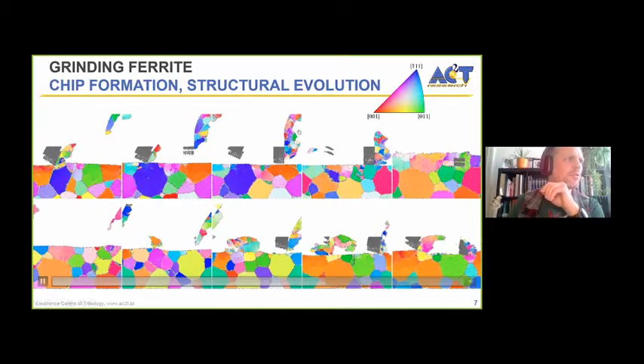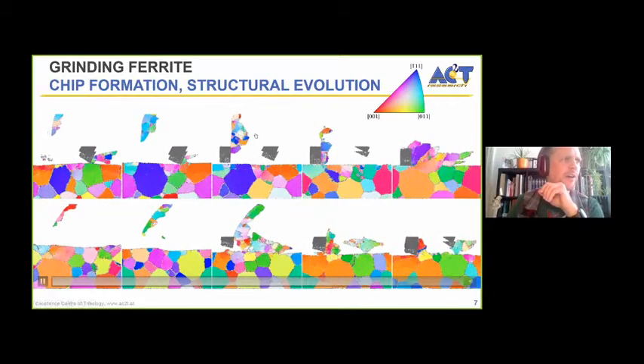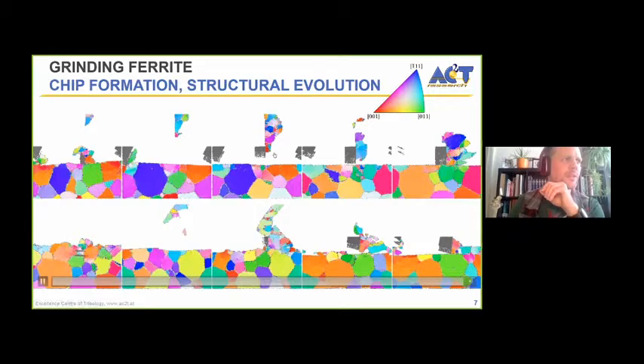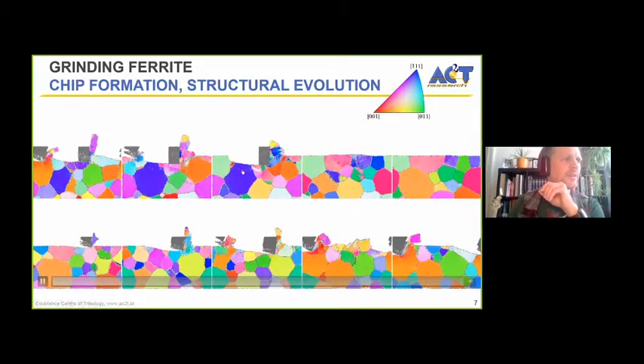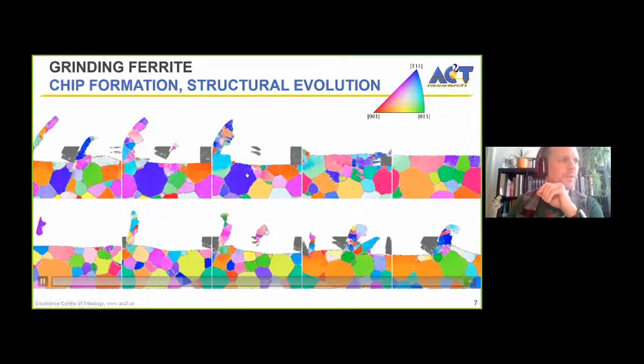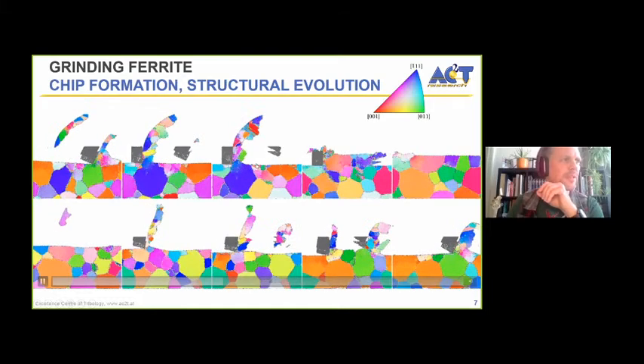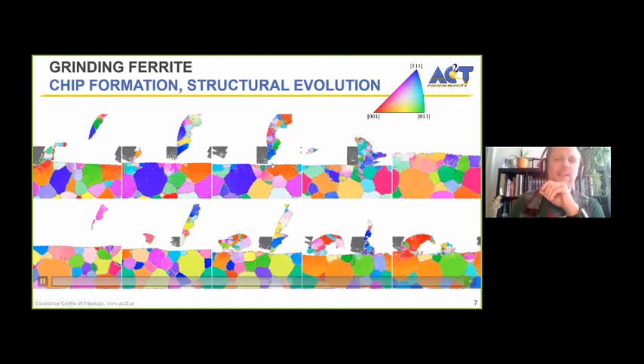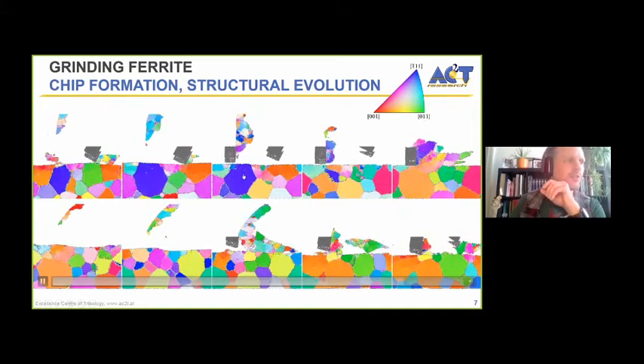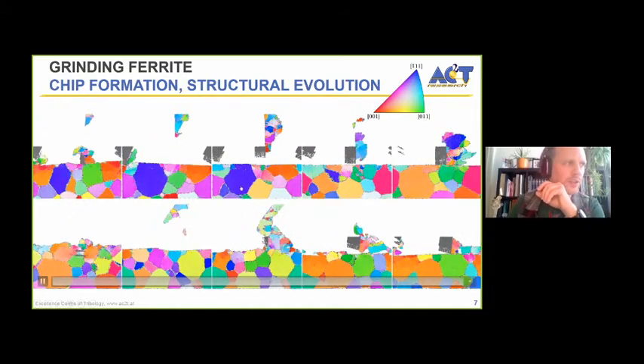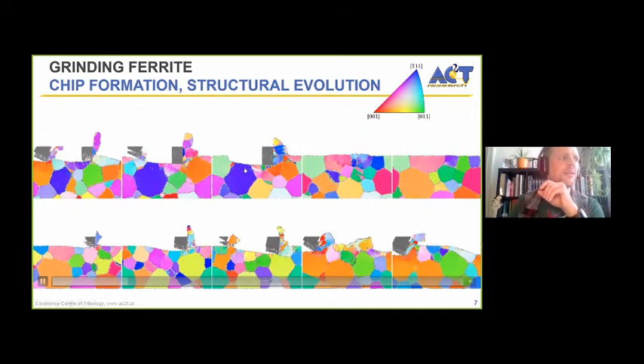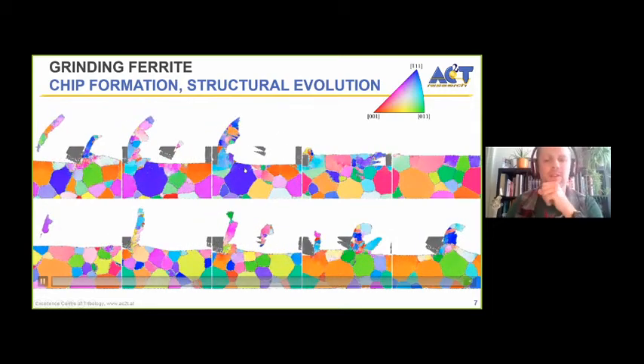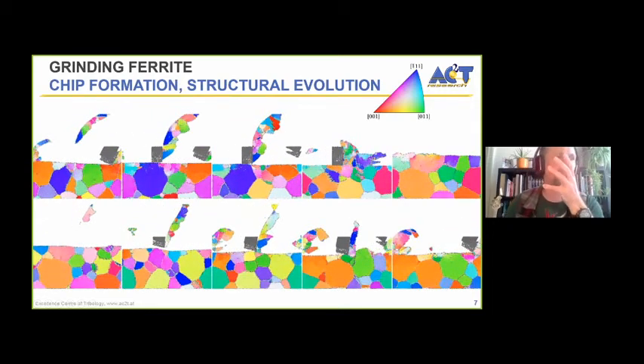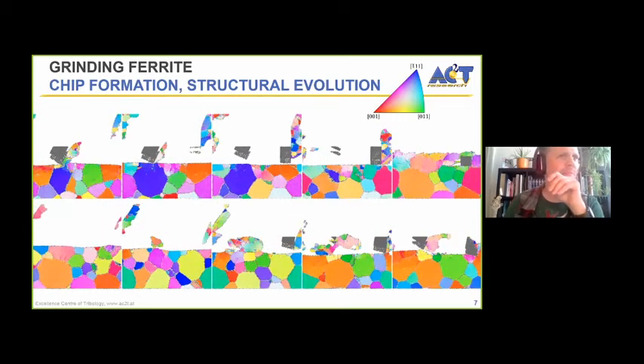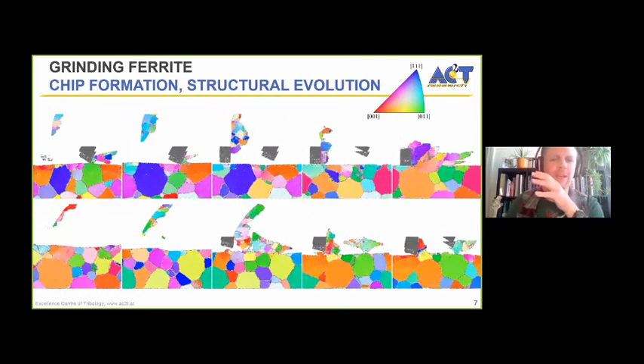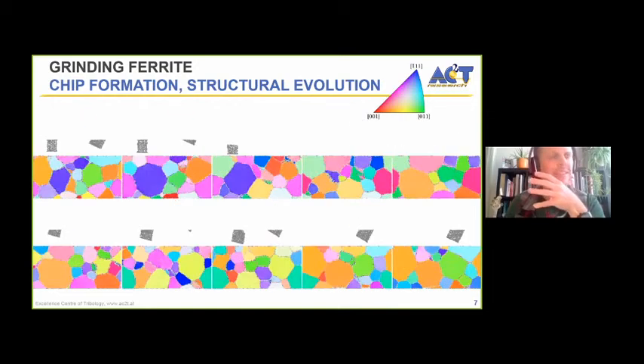You can see how the grains arrange, how fine-grained actually the chips are, how the dislocations come from the surface, from either the leading or the trailing edge of the abrasive into the surface. You can check if they are stored in the grains. You can see if the surface sort of gets annealed afterwards. If something seems funny to you, sometimes the grains or the abrasives seem to be coming sideways a little bit